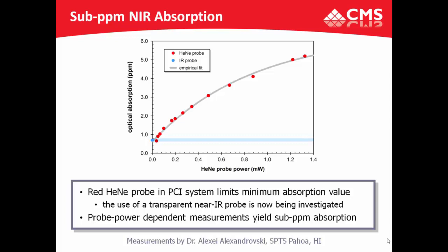So it turns out we have a background flux of impurities in the chamber. The final outcome was to pull the chamber walls, pull the excess sources that we are not using, and then just grow as fast as possible, reducing the incorporation of the background flux. Once we have that process dialed in, this is an example of a measurement on the best film that came out of that growth campaign.